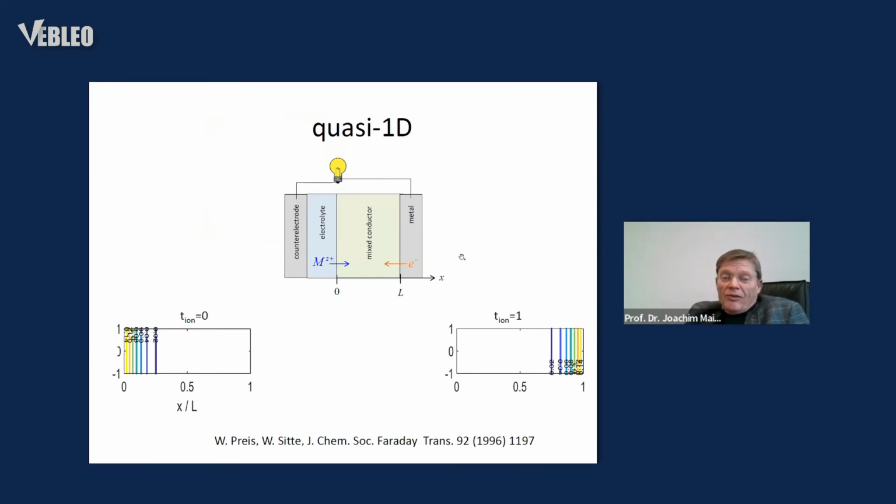And again, as far as the kinetic modeling is concerned, not very much is done in literature, even though the whole world deals with lithium-based batteries. So this is our electrode. The electrons come from the metal side and the ions come from the electrolyte side. So what happens if your mixed conductor is a good electron conductor? The electrons are fast, so obviously everything starts from this boundary into the interior. So it's a diffusion of M, which is M plus and electron, into the interior from the left to the right. It's called a chemical diffusion, ambipolar diffusion.